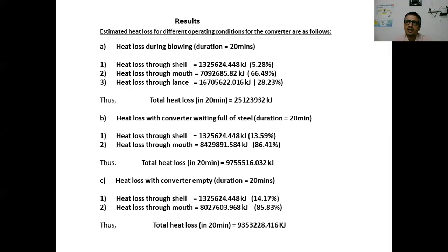For example, in the calculation, I have assumed some thickness of the refractory lining of the converter vessel, but as the converter campaign life goes on, the thickness may decrease. So for an older converter, the heat loss to the shell may increase, and in the overall sense, the heat loss in an older converter may be more as compared to a new converter.